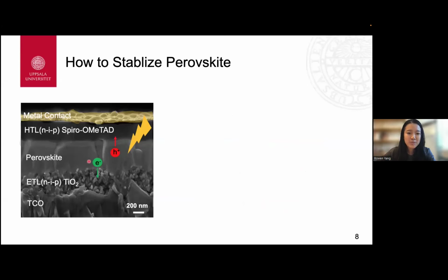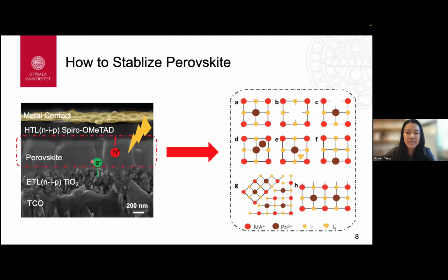In single junction perovskite solar cells, both efficiency loss and degradation in general are initiated at grain boundaries and surfaces or interfaces of the perovskite layer, where defects and mobile ions tend to accumulate under external stress. Therefore, suppressing the perovskite bulk as well as its adjacent interface defects, along with inhibiting different kinds of mobile ion migration, is very critical to achieve perovskite solar cells' long-term stability.